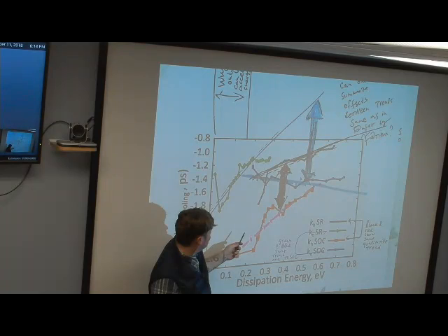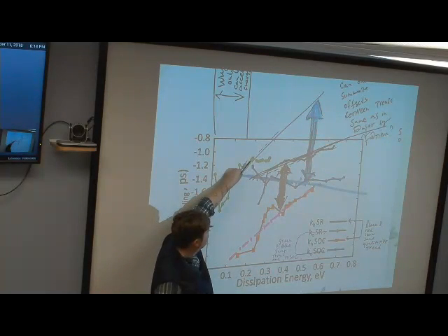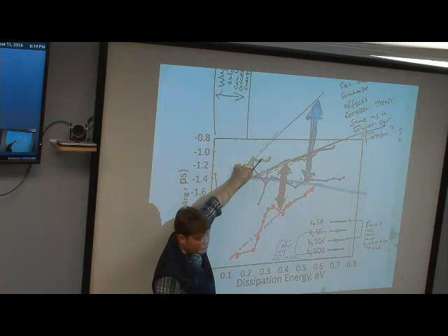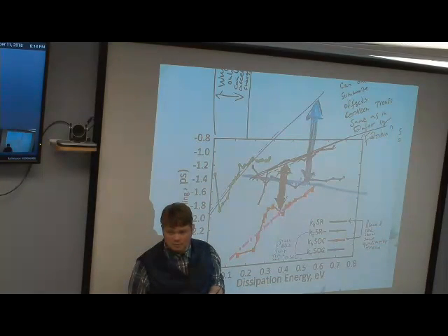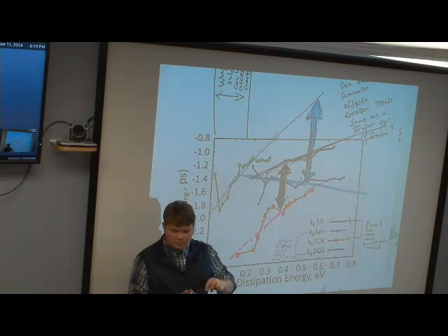But for holes we are fine, but for electrons, the qualitative trend changes. It goes from expectations along the gap law to the opposite. And typically it happens when the density of states substantially increases. The gap law applies when there are subsequent transitions between states that are offset from each other by energy, and the opposite trend is when there are dense states and one can go in parallel pathways.